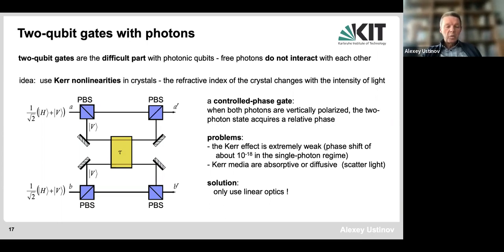So this is a very simple, intuitive explanation of what the Kerr nonlinearity is, but you can already guess that the nonlinearity from a single photon will be really tiny. And in fact, this Kerr effect for optical photons is extremely weak. The phase shift in the single photon regime is as tiny as 10 to the minus 18. And also the Kerr medium is absorptive and diffusive, so basically light is often getting scattered. There have been many attempts to find more efficient ways of making photons interact, for example, using nonlinear elements such as quantum dots. But sending two photons into a single quantum dot is possible, though it doesn't really look very scalable until now. So therefore, 2-qubit gates with photons still remain an unsolved problem, and photonic quantum computers function in a different way.